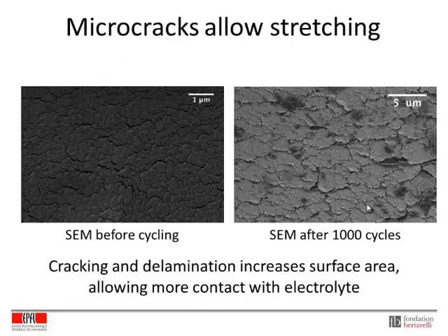So how do our electrodes stretch? They're enabled by a system of microcracks, which you can see in both of these top-down SEM images. The gold, which is much stiffer than the PDMS, forms a percolating network on the substrate, and as it elongates, the metal twists and deflects away from the PDMS while still being bonded to it. At the same time, over many cycles, the general morphology of the microcracks changes, and you can see the SEM on the right side.